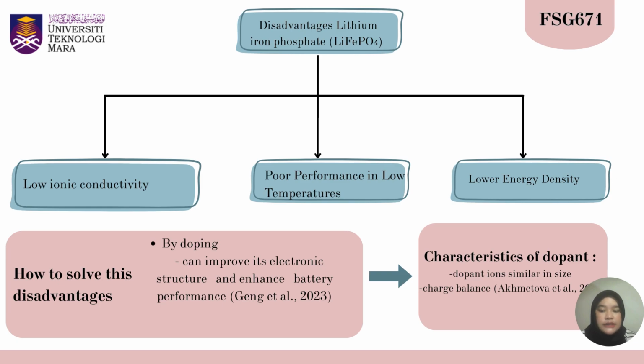So how can we address this disadvantage? One effective method is through doping, a process where foreign atoms are introduced into the LiFePO4 structure. Doping can improve the electronic structure and enhance the battery's overall performance. For doping to be successful, the dopant's ion should have certain characteristics. The first is that their ionic size should be similar to the ions they replace to avoid crystal distortions. The second is that they must maintain the charge balance within the structure.